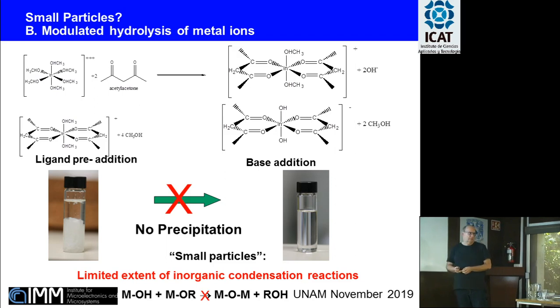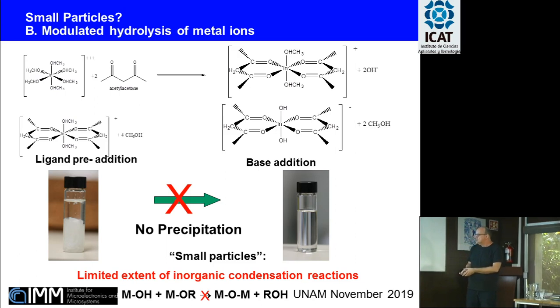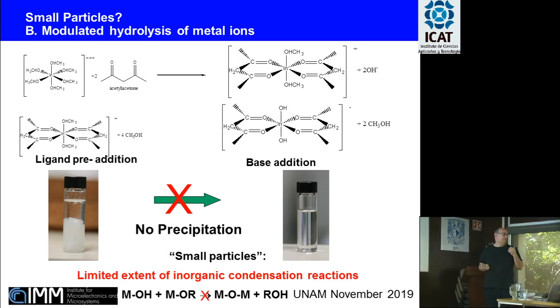So, we define our small particles as those that are obtained when these condensation reactions that result in precipitation are limited, so resulting in a clear, transparent solution. So limiting condensation reaction, limiting the Sol-Gel process. What is the relationship with all the presentation that I've been doing before? It is that these procedures are the same that we developed for thin films. So once we have developed the principle, in the case of cadmium selenide, we could apply this principle because we had already defined our small particles. They are those which are generated when the Sol-Gel process is limited to obtain a solution without any precipitate.